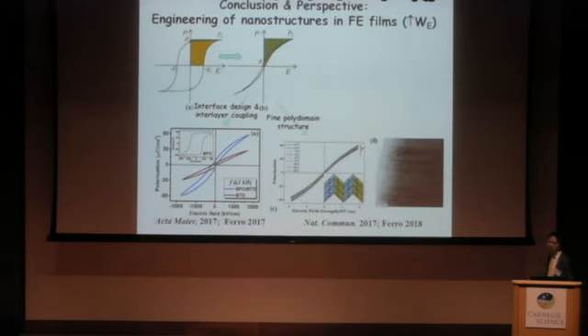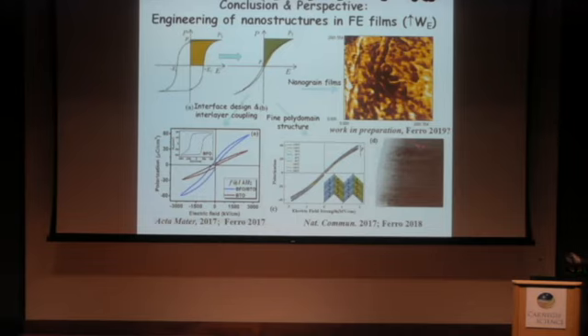So with that, I'm going to conclude my talk here. Last year, I actually presented some work of utilizing interface coupling. I grow a bilayer BTO BFO film. I show that I can significantly improve the energy density of a BTO almost 60%. And this year I show you that I can engineer the polydomain structure in BZT films to achieve very slim hysteresis with very high energy density. And in the future, hopefully, if I'm lucky enough, I present again next year of how to utilize nano-grain engineering to achieve the same kind of PE curves. With that, I thank you and I welcome your questions.